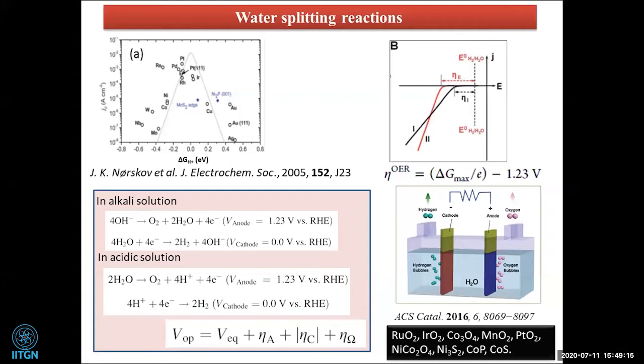We know that the oxygen evolution reaction is the most sluggish reaction in water splitting, because it involves a 4 electron process. If you see the voltage here, oxygen evolution takes 4 electrons and needs more energy, that is 1.23 volt, and hydrogen evolution takes 0 volt. That is in alkaline solution. In acidic solution, you can see this is the voltage.